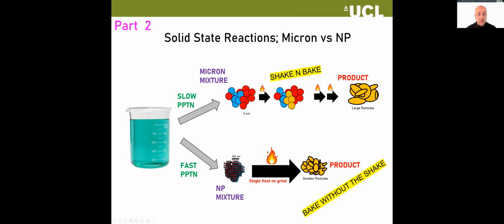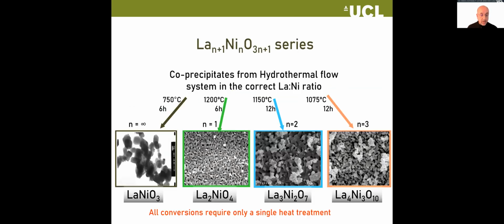as a few nanometers cross section of those individual oxide or solid solutions, then there is no need to grind them, because each one of these blue ones has a very short diffusion distance to react with a red one, and therefore there is no need to grind. And this actually works every single time without failure, as long as you're at the right thermodynamic conditions, of course, and that you've given it long enough to react. Those are the only requirements. So we call this bake without the shake.